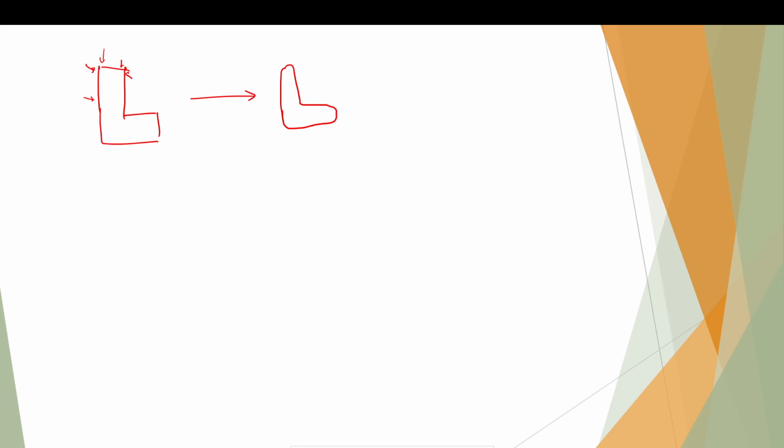Similarly here, and also sometimes we might have patterns very close to each other, and sometimes we might have a very standalone line. So the way the standalone line is transferred to the resist might be different from the way the closely spaced pattern is transferred, and that's also because of the same reason. Light passing will see more obstruction in this case compared to this case.